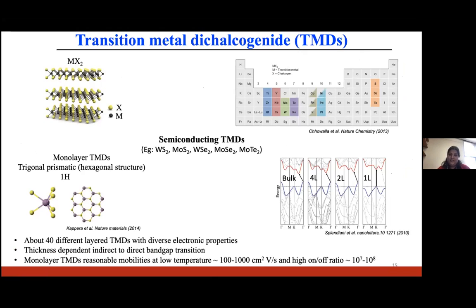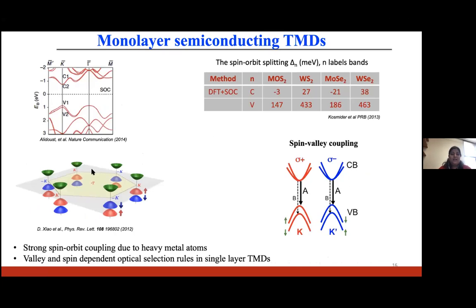But what we were interested in is the semiconducting TMDs like WS2, because in them, we have an interesting transition from indirect band gap to a direct band gap as we thin down the sample. And in addition, because it has a very heavy metal atom, we see that there's a splitting in the valence band. For WS2, the DFT calculation shows that it can be about 433 meV. And in addition, because of the inequivalent valleys in the single layer TMDs, we have an additional valley degree of freedom.